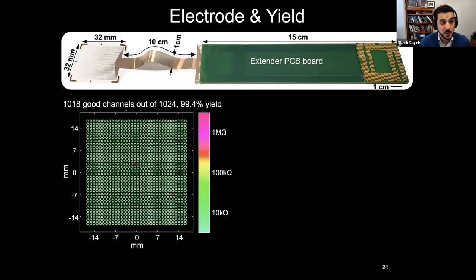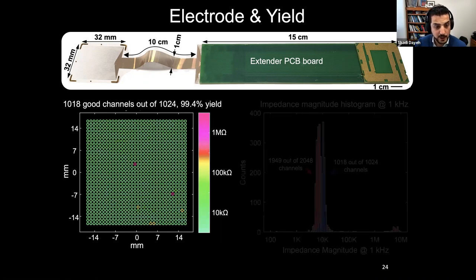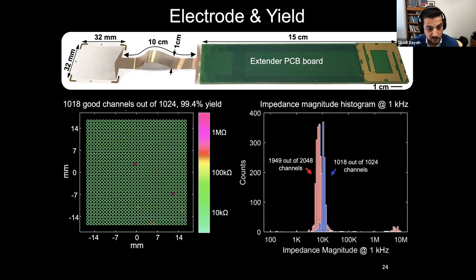All right, so how about the yield of impedances? Usually we get over 900 channels of working devices, that is with impedances of about 10 kilo ohms for a 30 micron diameter contact. And we are showing here the best devices. So in good days, we could get up to 99.4% yield or so. This is both for the 1024 grids and for the 2048 grids, and very tight distribution of the impedance.